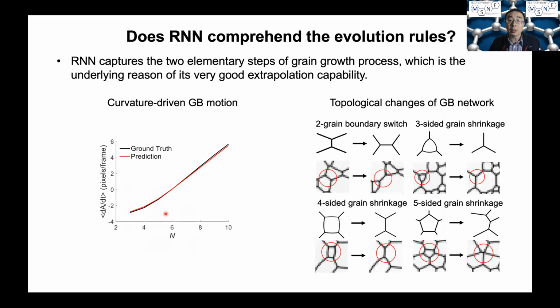And then we did some more digging into the data, into the performance, and we think the reason it's able to do a good job is because the RNN model can capture the evolution rules of the grain growth process. Right. So we have the following reason to support this claim, because we know the grain growth process consists of two elementary steps. So one is the continuous evolution, a continuous shrinking or expansion of a grain based on the curvature-driven grain boundary movement. Right.